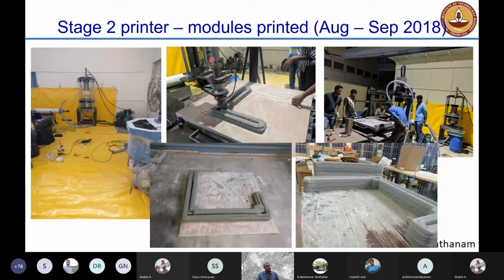You see here the same printer is now being used to actually print the concrete. You see several modules now getting printed. And we essentially ended up printing modules which were nearly 30 centimeters in height, or which had 20 layers of 15 millimeter depth each. Okay. These 30 centimeter modules were then taken to site and then assembled together. I'll show you a picture of the assembly.